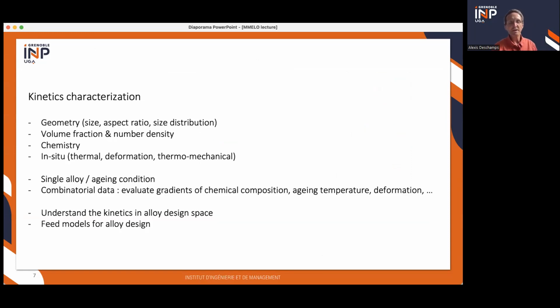So basically, what do you want to know when you want to understand kinetics? Well, you want to know different parameters of the phases that you're transforming. So this can be geometry, the size, maybe aspect ratio, size distribution. And this can be how much, so volume fraction, number density. And this can be the chemistry, because in many cases, you're not really sure about the chemistry. You can have some substitutions, you can have chemistry evolution during time. And you want to know this also.